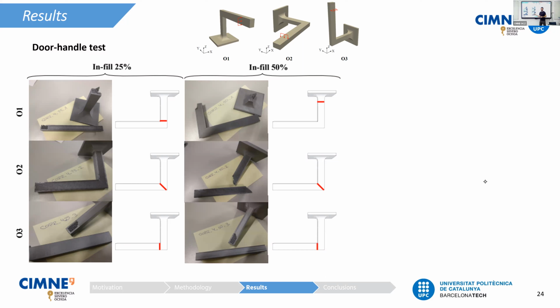If we take a look at the experimental results, we have printed 3 different orientations, orientation 1, 2, and 3, and we have analyzed 2 different infill densities, 25% infill density and 50% infill density. And what we can see is that the failure not only depends on the orientation, but also on the infill density that was used. For example, for the first orientation, we can see that the failure occurs at the corner and, let's say, horizontally, meaning it follows the direction of the layers. However, this happens only when it is printed with 25% infill.